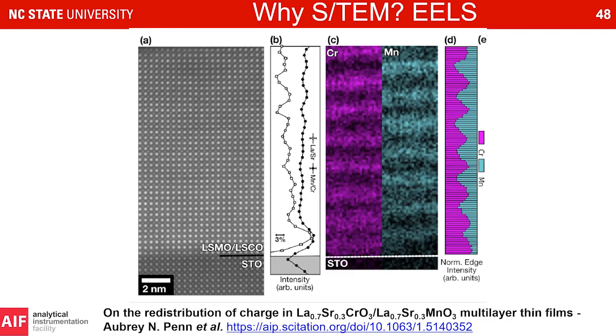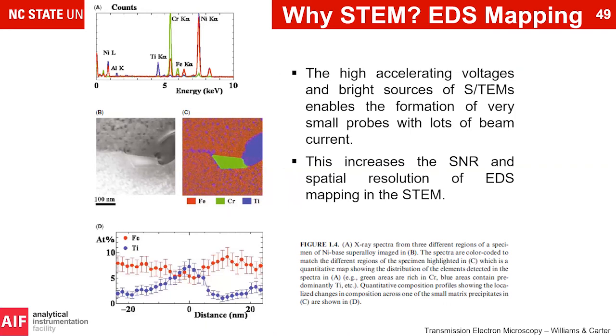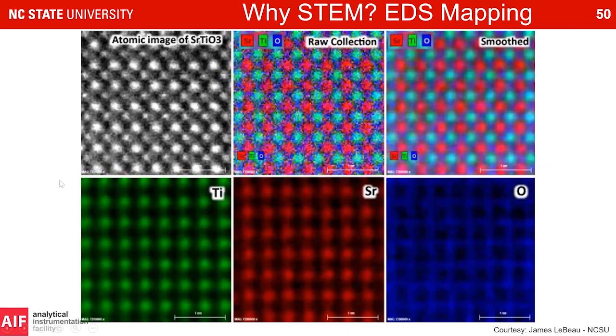EDS in TEM: many students do EDS in the SEM, but in SEM the resolution of EDS is limited not by probe size but by the sample interaction volume. In TEM, with thin samples, our interaction volume is very small and we can achieve atomic-resolution EDS. This work by Jim LeBeau and students (formerly at NC State, now at MIT) shows raw EDS maps of strontium, titanium, and oxygen in strontium titanate at the atomic length scale — atomic chemistry.